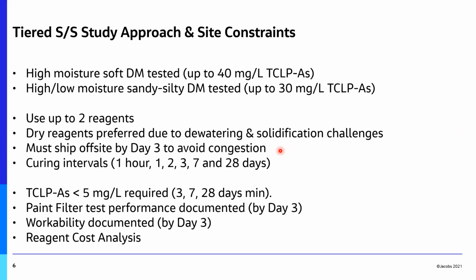We had 11 bins with 1,700 cubic yards capacity each. And if you got out of cycle and you failed your arsenic criteria on those, the site backed up immediately. In fact, the site was completely shut down because all the bins were contaminated when exceeded the TCLP limit when I joined the project. So the idea is get that off-site as fast as you can.